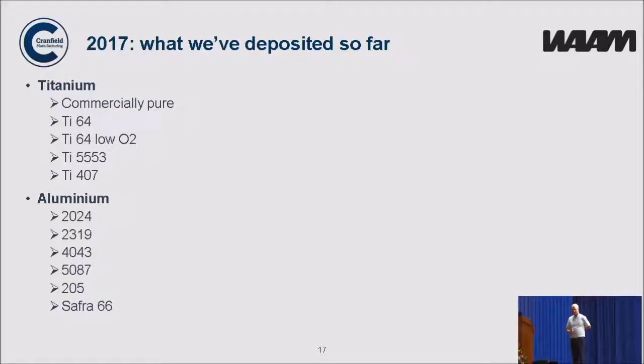What about the different kinds of materials? Well, pretty much if you can get welding wire, you can deposit it. So, of course, the focus for us has been on the titanium because that was what the funding was for mainly. So we've looked at commercially pure titanium, standard 6.4, low oxygen and high oxygen 6.4, 5553, which is a higher strength beta alloy, and also 407, which is a higher toughness material but lower strength.